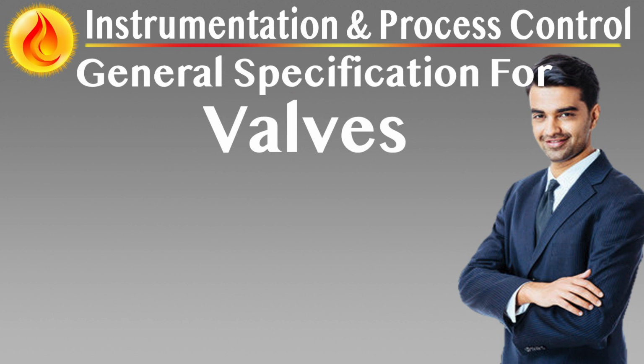Where CRA body valves are commercially unavailable in large bore sizes, typically 8 inches and above, CRA-clad or overlaid carbon steel valves may be accepted, subject to technical approval. All CRA materials and procedures must be fully traceable and validated by the supplier through mechanical tests and corrosion performance data. Matching of base metal and cladding to trim material must also be ensured for wetted surfaces, flange facings, and pressure boundaries to prevent galvanic corrosion and ensure uniform service life.